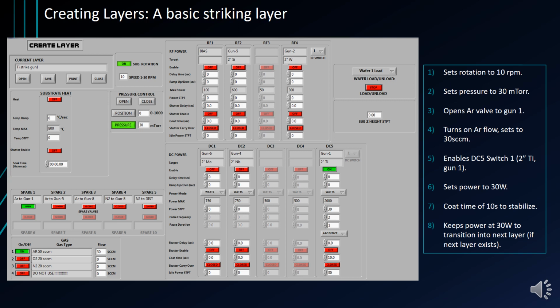It sets up the gas flow and pressure in an appropriate region for ignition, and then turns on a relatively low power. We choose to keep the power on into the next layer because we want to keep the plasma on while we enter a better process region for sputtering onto our substrate.